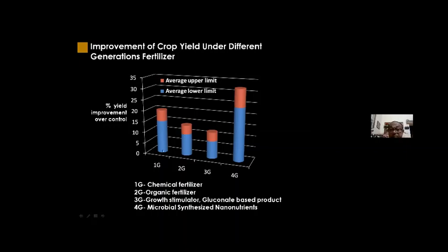Now, I have compared yield with different generations of fertilizer. Chemical fertilizer is the first generation fertilizer. Overall, for all crops on average, you don't expect more than 14 to 18% yield increase. In case of organic fertilizer, the second generation, you may expect only 8 to 12%. Third generation fertilizer, growth stimulator or gluconate based product, you can expect 5 to 10% more yield. But we found that microbial synthesized nanonutrients, if you use them as fertilizer, give 24 to 32% improvement in yield.